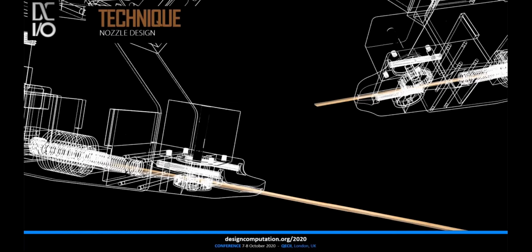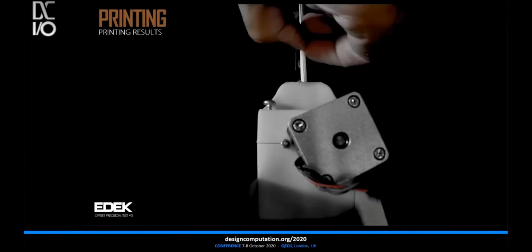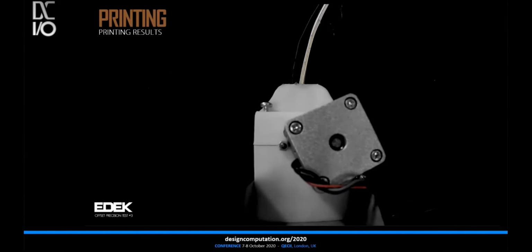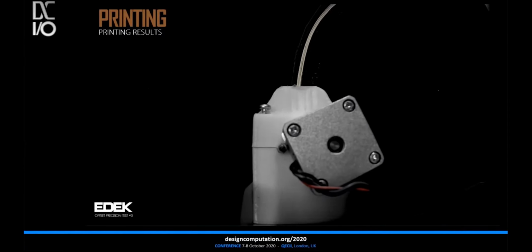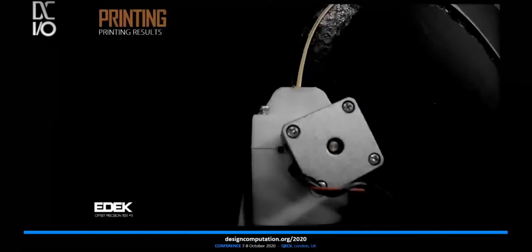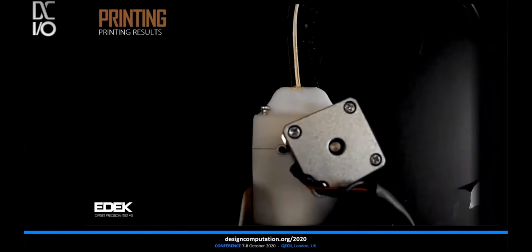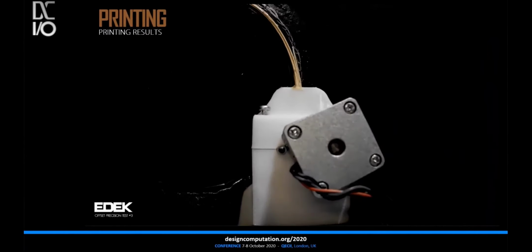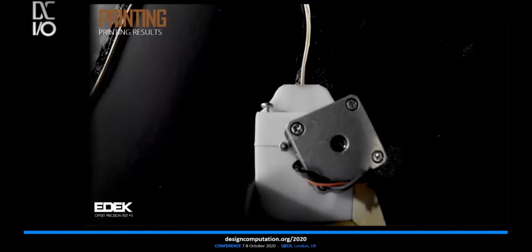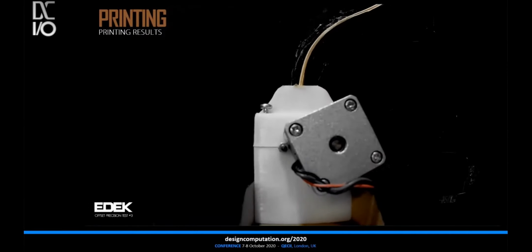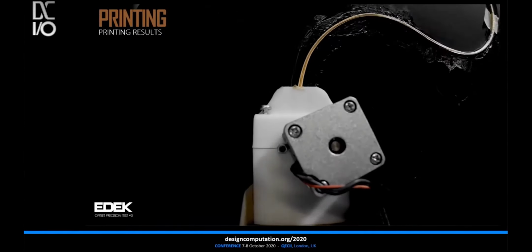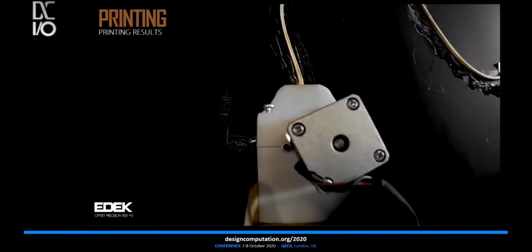The nozzle consists of one silicone roller, one geared roller and one funnel. Together, they press and guide the strings together to one compound heated string, while the funnel guides the filament to the print bed and applies slight pressure to it. The idea of combining the strings within the extruder addresses the individual string length within a printed surface curvature. By combining the laminated strings with heat, the printed and cooled down extrusion can keep its given curvature.